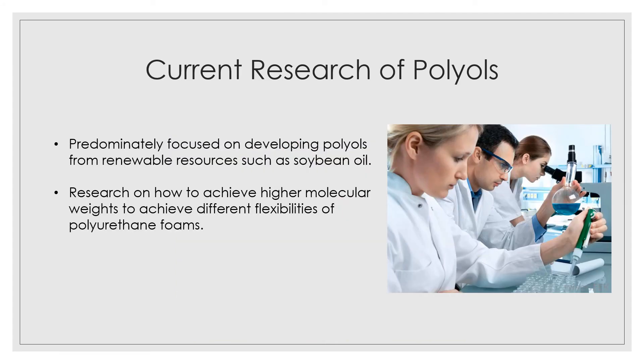Now onto current research of polyols. As mentioned prior, the difficulty with these renewable polyols is the uneven saturation of the double bonds. This remains a high level of focus for researchers at the Kansas Polymer Research Center located in Pittsburg, Kansas. Zoran Petrovic has spent much of his time comparing the mechanical and insulating properties of soy-based foams versus traditional PPO foams. Petrovic's studies have shown that soy-based polyols currently do not have enough hydroxyl content required to produce a sufficient degree of cross-linking for a rigid foam product. By analyzing the OH number of the polyols and adding more water as a multifunctional cross-linker, these researchers were able to bring the viscosity of the soy polyols to a working range and prepare various types of polyurethane foams through methods such as chemoenzymatic epoxidation, ozonolysis, and hydroformylation.